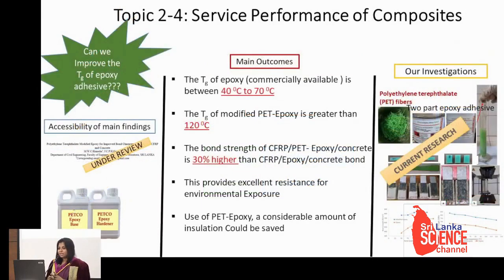Then we switch to our next option, improving TG of epoxy adhesive. So we have seen PET fibers, that's a waste material, and it possesses good material properties and thermal properties even at elevated temperature. So we thought to use PET fiber with some combinations to modify the current epoxy adhesive used in the industry. After a series of testing, we found a good product, actually.